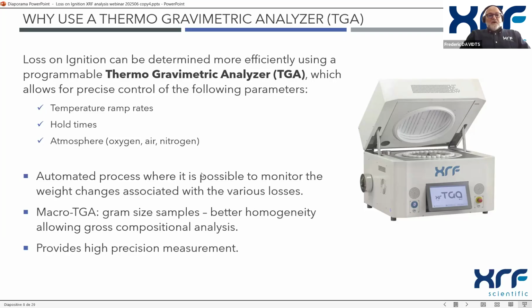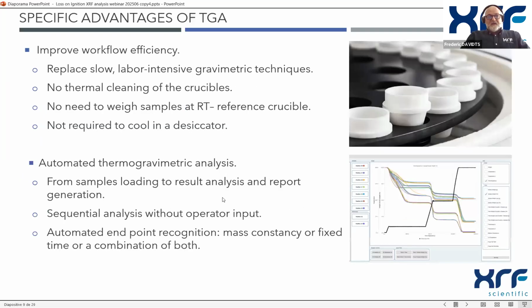So the TGA here, in this case, is a macro TGA, not a micro TGA. Macro TGA means that we are working with gram-size samples. So the big advantage is that we have better homogeneity, more quantity, a larger sample, and it's perfectly made for gross compositional analysis like ash, LOI, volatiles, moisture. And this technique provides, of course, high precision measurements.